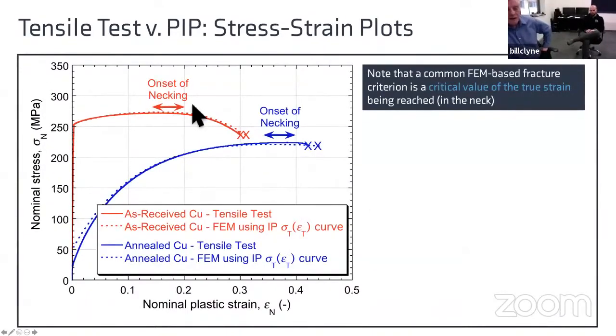Now, the bottom line is what actually happens if you take an unknown material, you make an indent, you carry out this process, and you end up with a nominal stress against nominal strain curve, which you can compare with a conventionally obtained one from a tensile test. So this is just a couple of examples. These are actually both copper samples. One of them as received, as extruded, so quite a high yield stress, not much work hardening. On the other hand, the same material after annealing, gets much softer, much lower yield stress, although it then work hardens a lot. And as you can see, you're getting pretty good agreement between the conventionally obtained curves and the ones just from indentation, followed by this iterative FE procedure. So that's the basic idea, and it does work, so to speak.